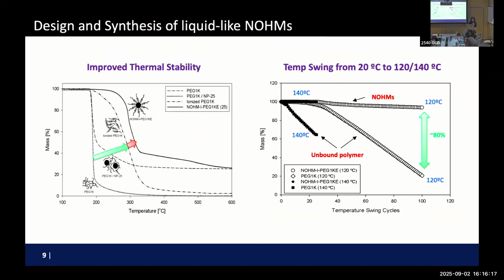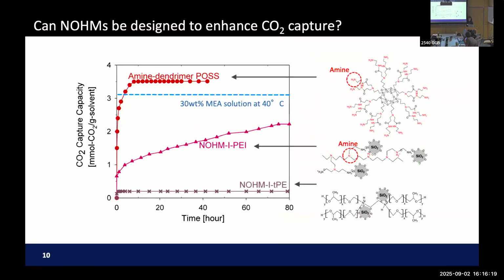Anyway, with a long story like that, the only thing we had to do was put a lot of amine functional groups, which we did, and as we expected, it really improved the total CO2 capture capacity, but it was expected. So we got really excited. I'm squeezing like 7-8 years of research into a few slides, right? So then I started thinking that, well, it's getting really exciting in terms of CO2 capture capacity, and it's a really robust material, selectivity is excellent.